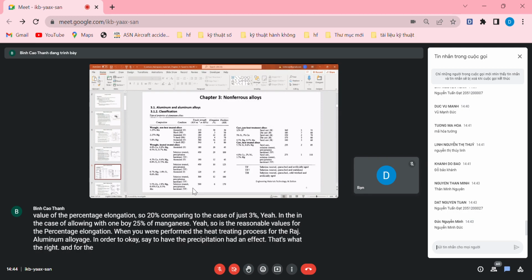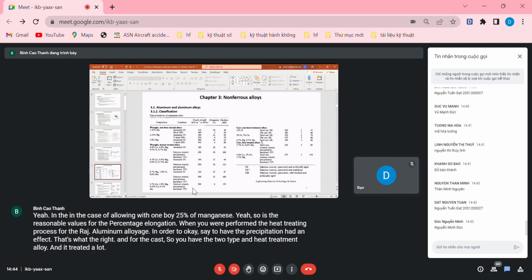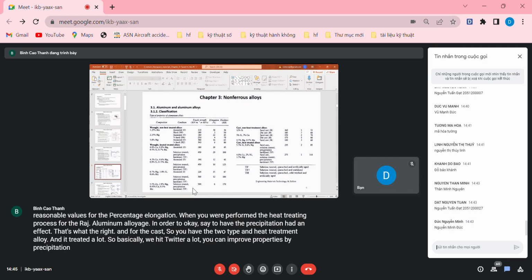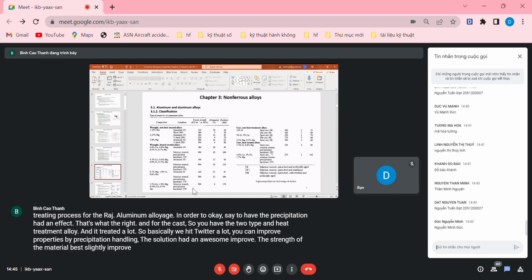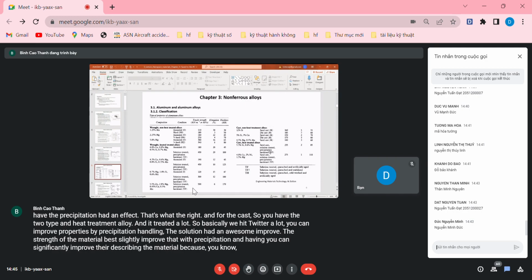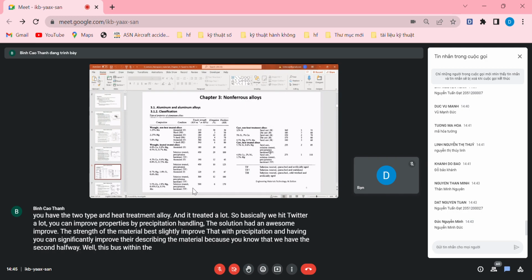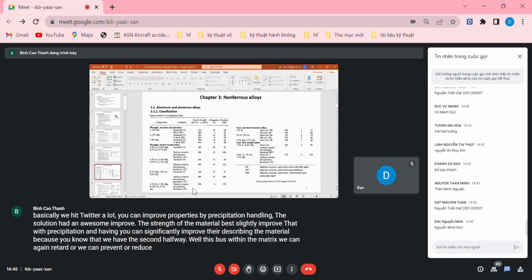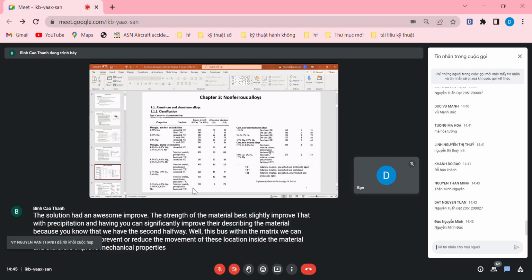And for the cast, you have two types, non-heat treatable alloy and heat treated alloy. Basically, with heat treated alloy, you can improve properties by precipitation hardening. Solution hardening can also improve the strength of the material, but only slightly. But with precipitation hardening, you can significantly improve the strength because we have the second phase well dispersed within the matrix. We can retard or prevent or reduce the movement of dislocations inside the material and therefore improve the mechanical properties of the materials.